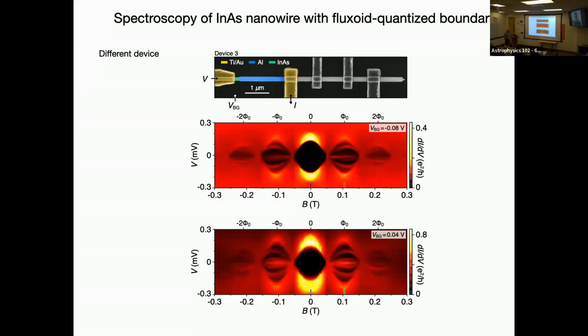A little bit hard to see with the lights on, but I'll just describe it. There's a superconducting gap with nothing sub-gap in it. Maybe there, not much of anything, but basically a low conductance gap in the zeroth lobe, where the proximity effect is effective and induces a gap inside of this core. But when you have one twist of the wave function going around 2 pi, you can say that the core doesn't exactly know how to get proximitized. It doesn't have a phase that it can pick up from the shell. It winds by 2 pi.